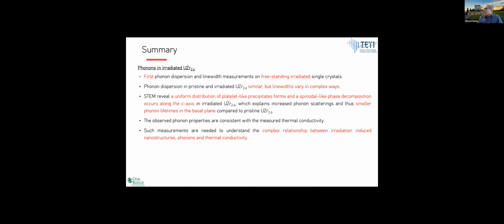And the observed phonon properties are consistent with the measured thermal conductivity. I didn't talk too much about it, but the electronic thermal conductivity is not really that affected by the irradiation. So we think that the changes are mostly due to the phonons, but there's a mix there, which makes it complicated. And so I think such measurements are needed to understand these complicated relationships in materials that are getting irradiated in a reactor or while being stored. And this is affecting temperature, safety, efficiency, and all that. So yeah, that's basically all I have.